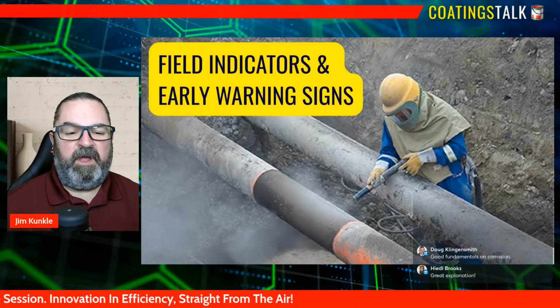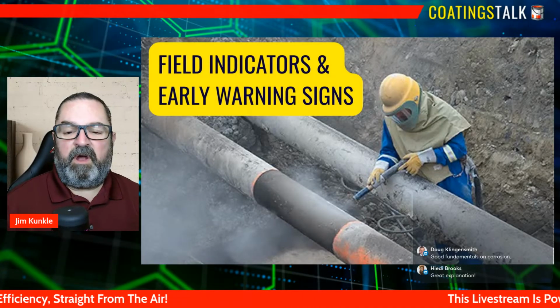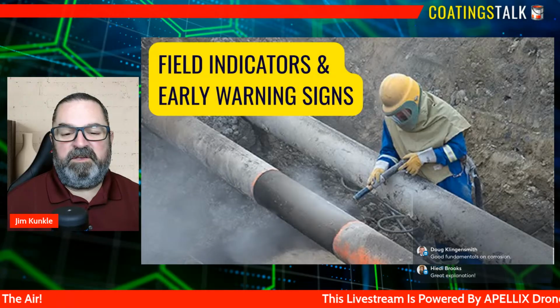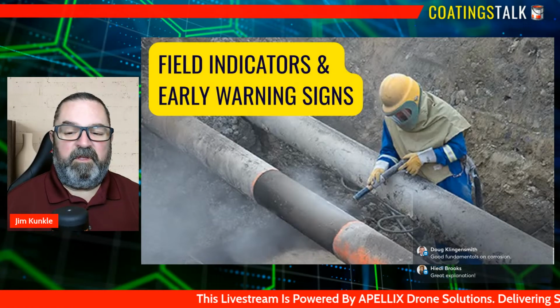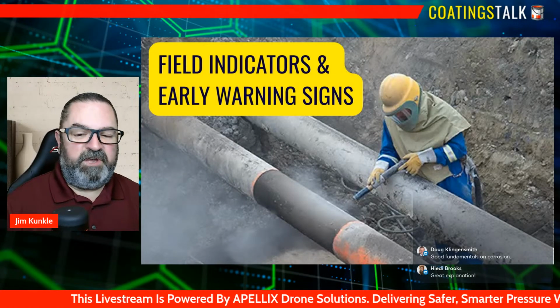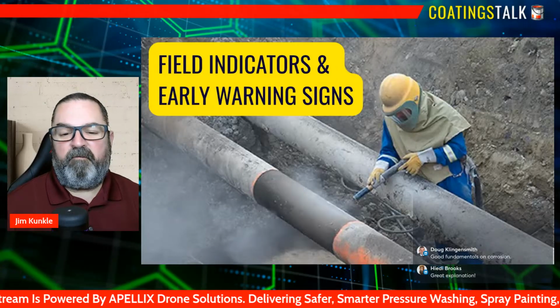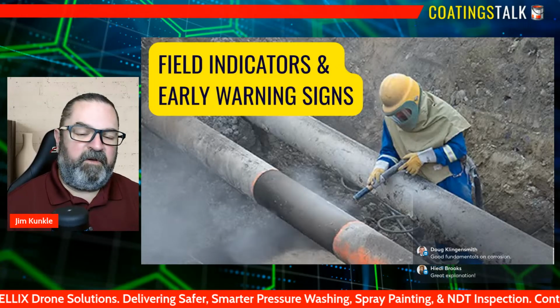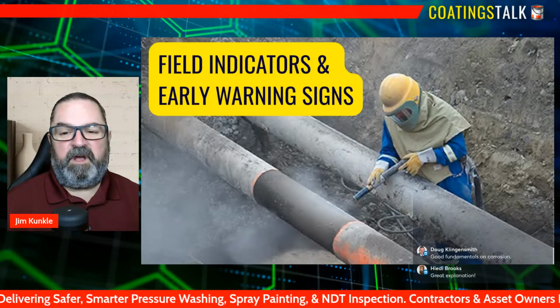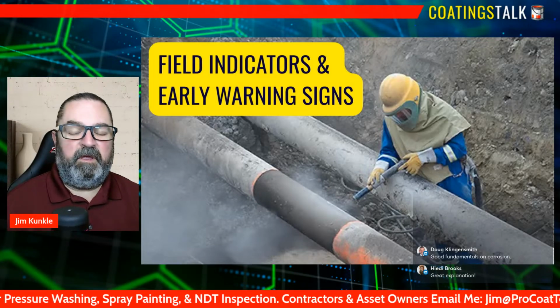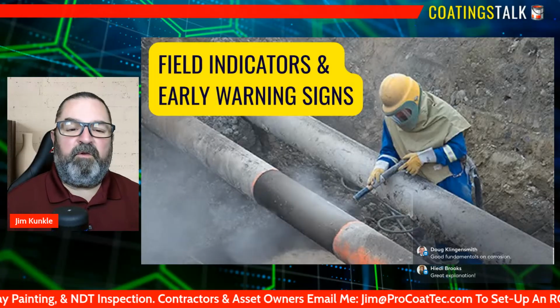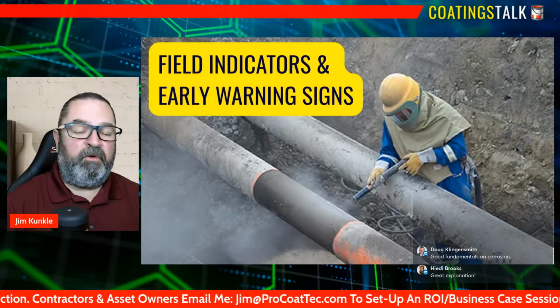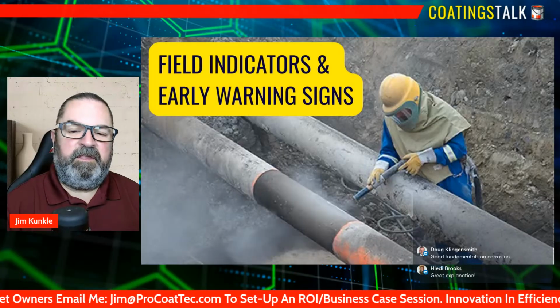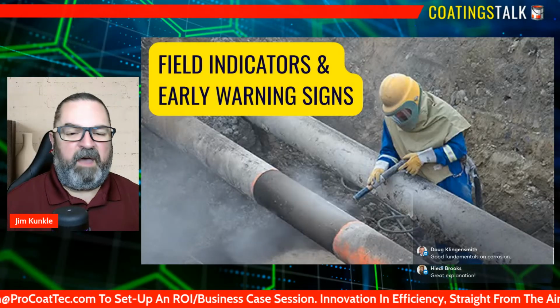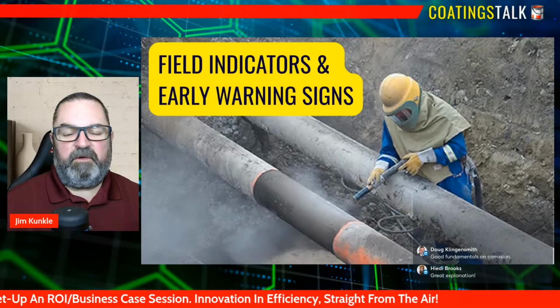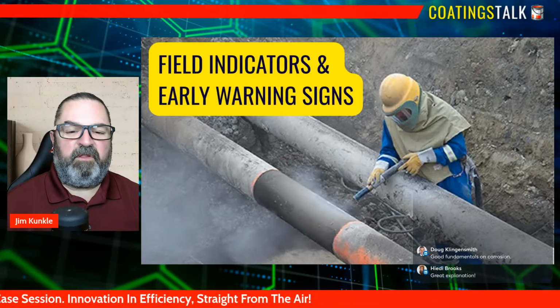Even minor discoloration, a faint orange tint, dark streaking, or unusual shading can indicate that oxidation has already started beneath the surface. When field teams learn to recognize these small changes, they gain the ability to intervene long before damage becomes severe. And coating failures are another critical early warning sign. Blistering, pinholes, cracking, peeling, or lifting edges are points where moisture intrudes or there's a loss of adhesion. These defects may look small, but they create direct pathways for oxygen, water, and contaminants to reach the metal. Once this happens, corrosion accelerates quickly.